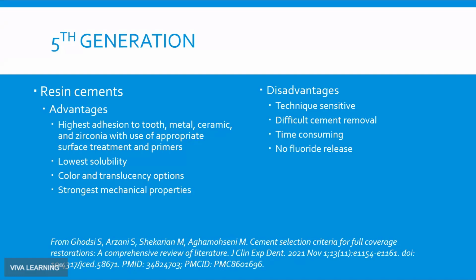The downside, of course, was that even though you could bond to other materials and teeth, every material requires some sort of preparation through use of a primer: multi-step etching and priming, silanating, priming. Every single material, metal priming, everything requires some sort of primer to achieve a bond. I remember doing the tin plating of certain gold to get some sort of bond to gold. So while it had some promise, it was certainly technique sensitive.